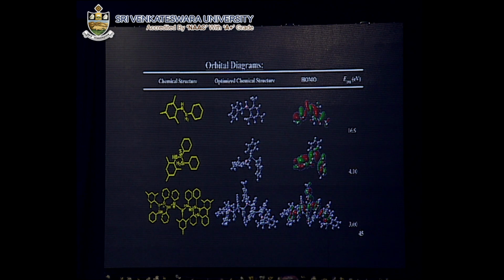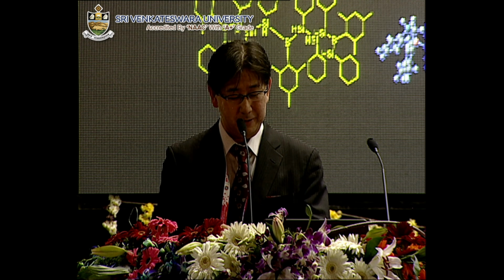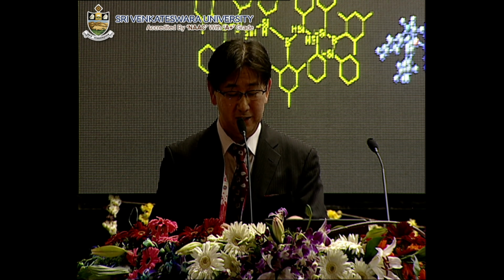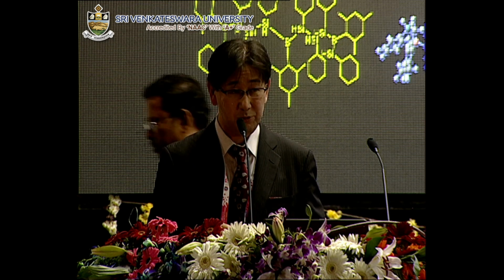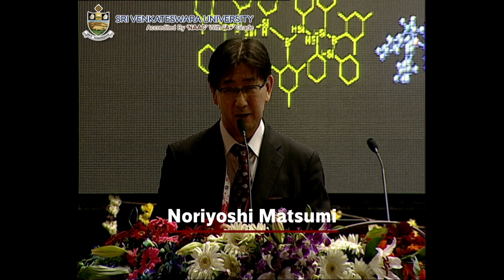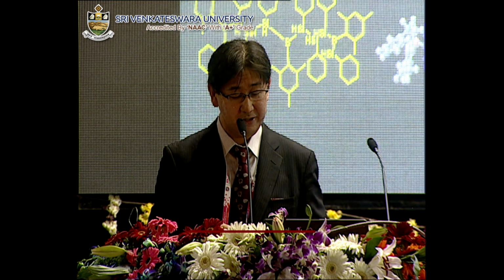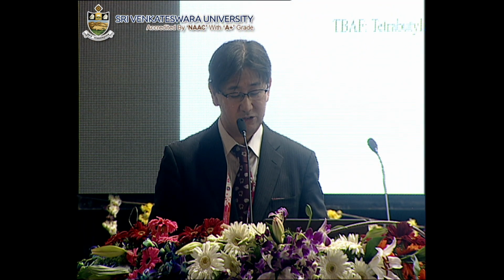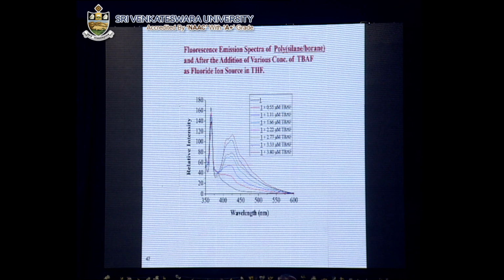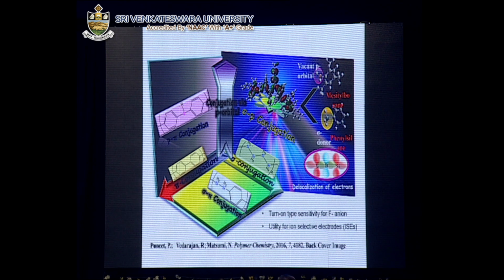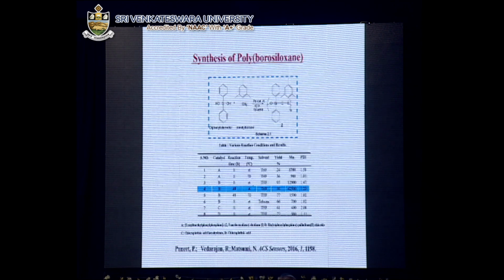The DFT calculation also indicates that with increasing chain length of the p-pi conjugation backbone, a marked decrease in the band gap was observed, showing that p-pi conjugation is prevailing in this system. This was found to be very efficient for turn-on type fluoride anion sensing at micromolar-order concentrations of fluoride anions. This is a novel mode of conjugated materials, and recently it was highlighted in RSC Polymer Chemistry as a cover image.